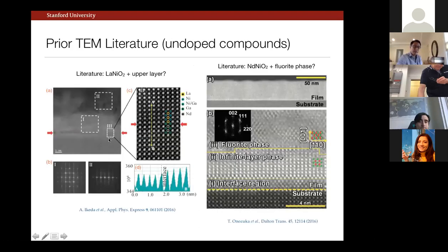I should also say that this was already discussed somewhat in the prior literature. So this is, for example, lanthanum nickel O2 thin films. This is neodymium nickel O2 thin films. There are many interesting details, but the point I emphasize here is the same thing that I just described to you, that in the vicinity of the substrate, you have this epitaxial stabilization of the infinite layer phase. Above that, you have various secondary or competing phases or decomposition products. For the neodymium nickelate, the same thing is observed. Okay.